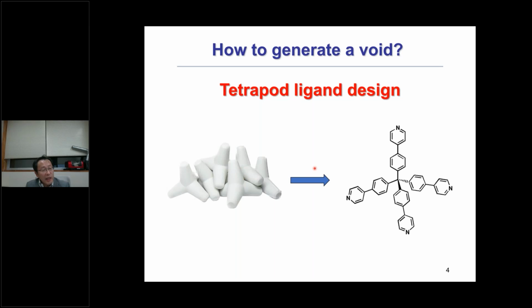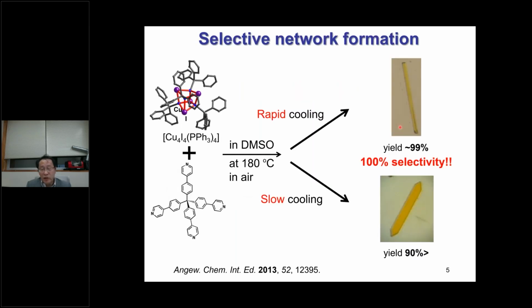First, we designed this Td symmetry, pyridine type ligand. This ligand has 4 hands as coordination sites. If you use this Td type ligand, you can easily make a pore, or channel. So let me show some examples. We use this Td symmetry ligand combined with this copper iodide cubane cluster, Cu4I4, and triphenylphosphine. This is the terminal ligand.